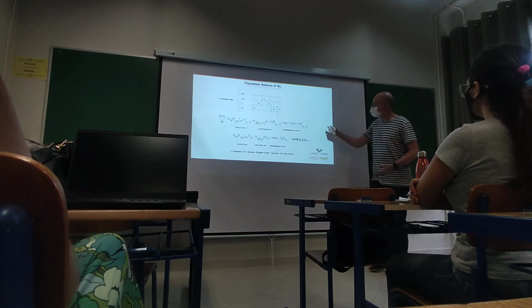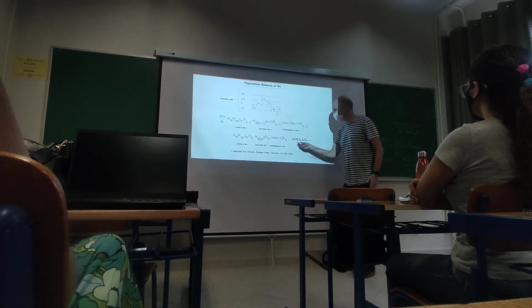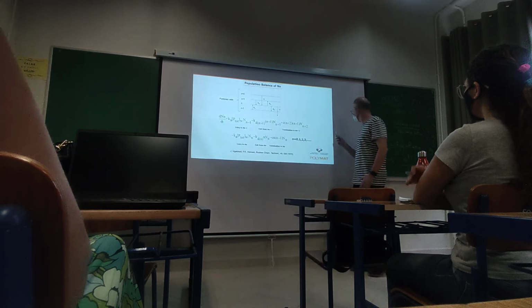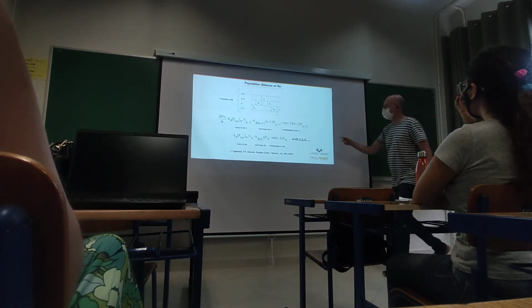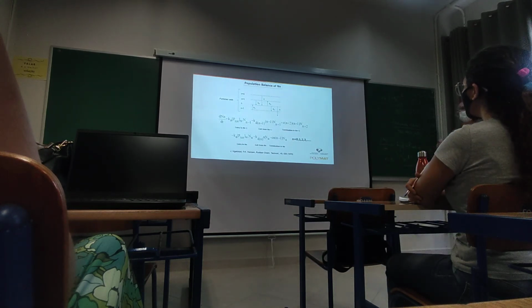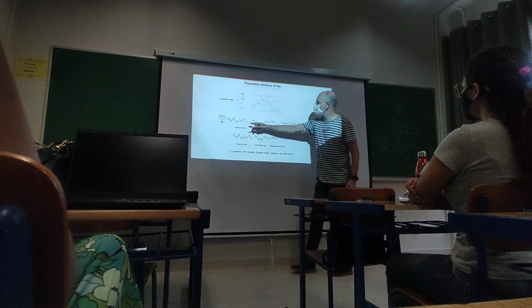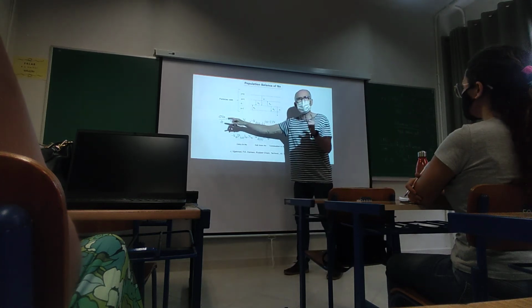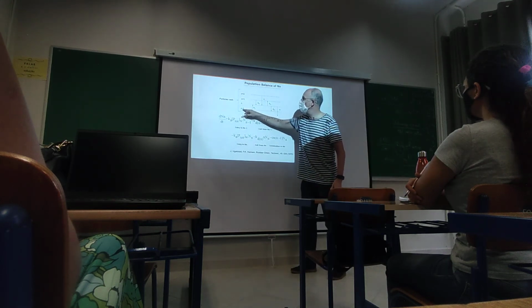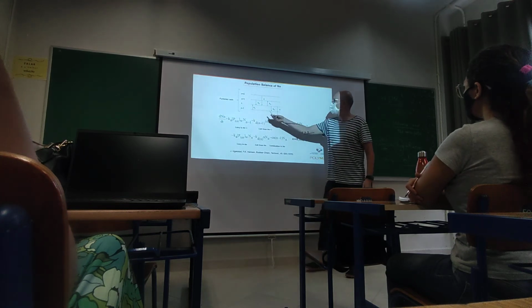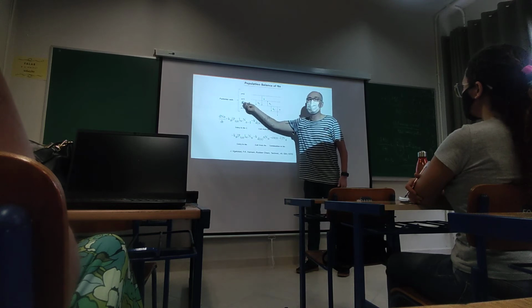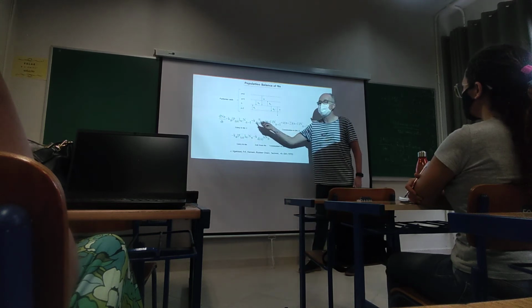Okay? This is the general term. You see here. So, the first terms are the generation, and the three negative ones are the rates of disappearance. The first step: a particle with n radicals can be formed if we have absorption in a particle with n minus 1 radicals. So, if we have particles with n minus 1 and they suffer absorption, they will become particles with n radicals. So, this is this term.